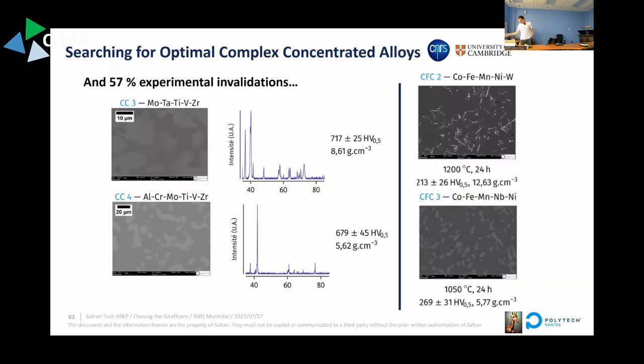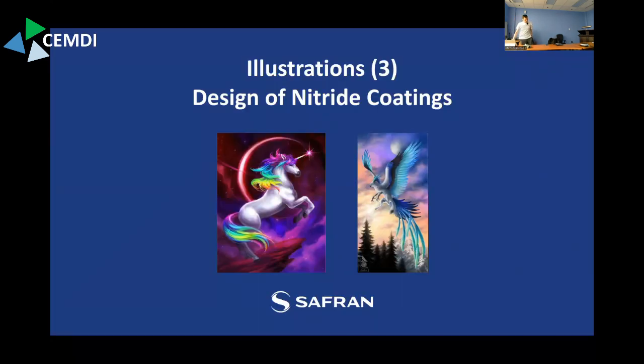We had a lot of experimental invalidation, basically 4 out of 7, which means we're not very good. But for a budget of 7 alloys out of the 10 to the 85, this is still an achievement, I think. And we're going to conclude with the nitride coating design.